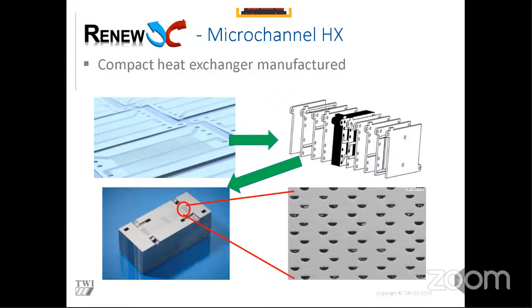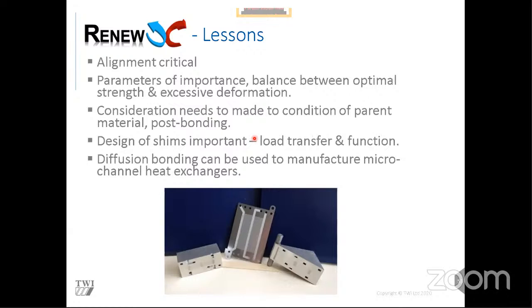It shows the principle. So the lessons of this project, some very big lessons. Alignment was very critical. Because we have very tiny features, you can see here how small the channels are. If you are slightly out by a tenth of a millimeter, you can have an issue. So building in some sort of alignment feature, such as a pin or a rod, as shown in this image here, is important. It's very important to balance your parameters, so you're getting really good strength for your joints, but you're not excessively deforming your channels. So you've got to balance strength versus deformation.